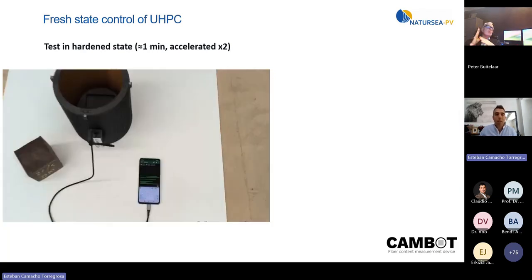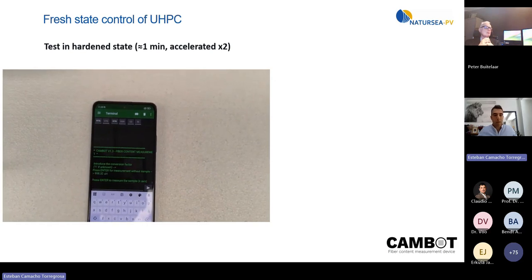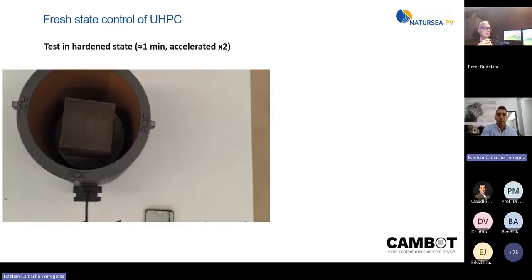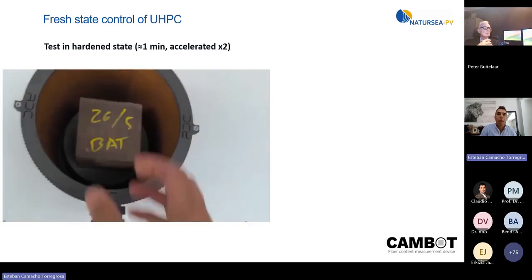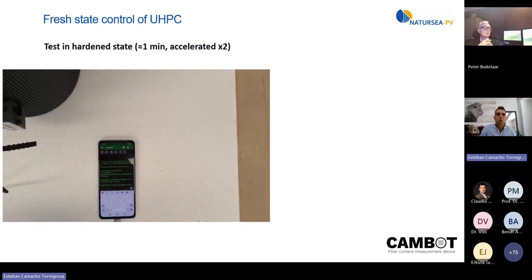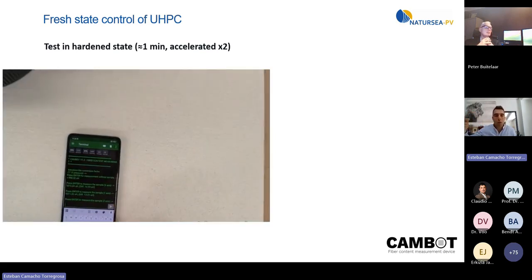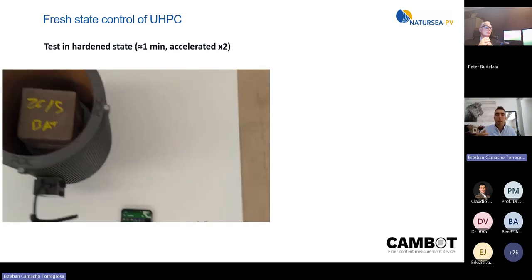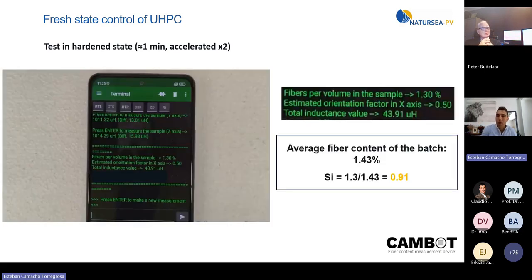If we want to do this test in hardened state, it's even simpler. Simply we fill cubes, and the next day we can obtain the same value. This is an example of an element which was too fluid, or more fluid than what we generally want, and the result is 1.3, while the fiber content of the whole batch was 1.43. So the segregation index is 0.91. So the last concrete that we were pouring had 9% fewer fibers than what it should have. Okay, this is already at the limit.